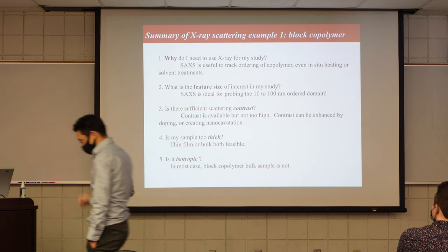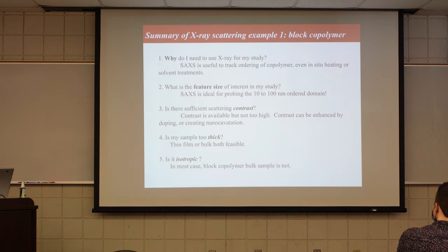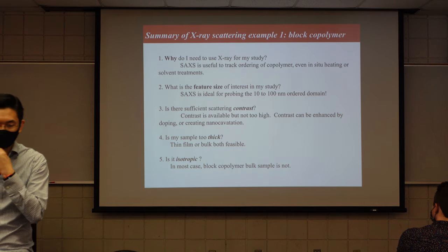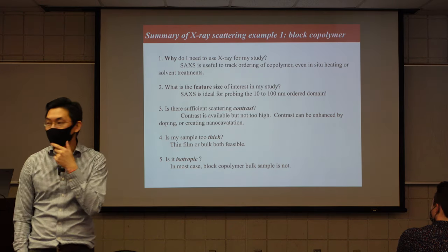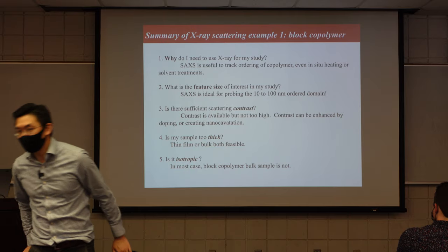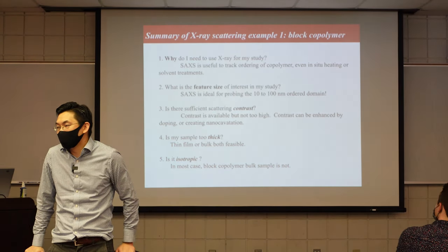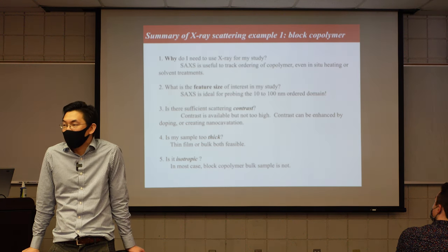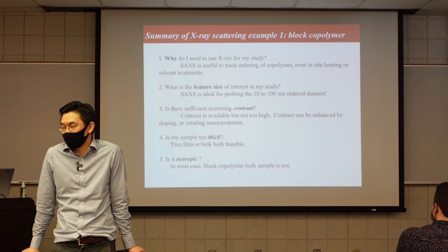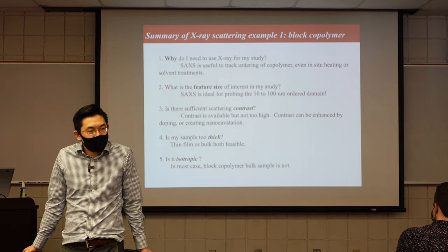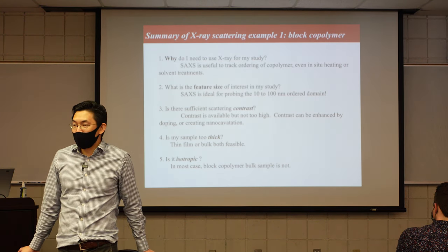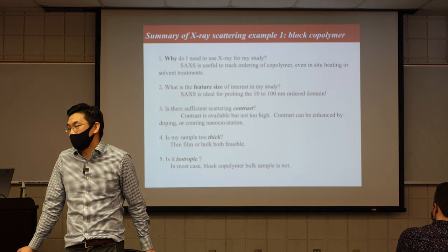Will, please. Is there any way that you could tell if there's any leftover solvent in the polymer when you're using X-ray scattering, or you can't really determine that? Possible. It's a little bit trickier to use X-ray just because the solvent scattering length density and polymer are close. But if you have a way, you can introduce a totally different scattering length density material that easily can be done. I'll tell you about some great work that has been done by Professor Thomas Epps at the University of Delaware.